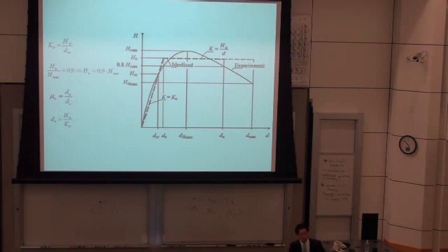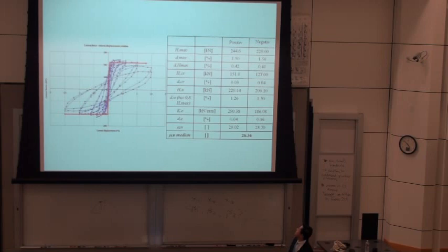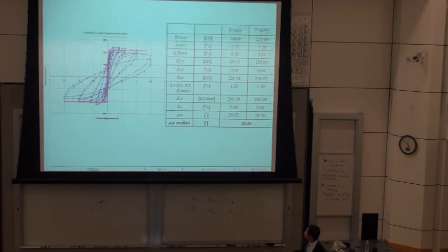You don't use more than 80% of the maximum horizontal force you could apply on the wall, because as I said, the horizontal tests are displacement controlled. Then you can define the stiffness, your initial crack displacement, the ultimate displacement, elastic displacement, and so on, in order to calculate your ductility, your mu. And in this case, just as an example, you have the hysteresis, you make the envelope, the bilinearization, you have all the values for the positive side and the negative side, left or right side, to get the ductilities.